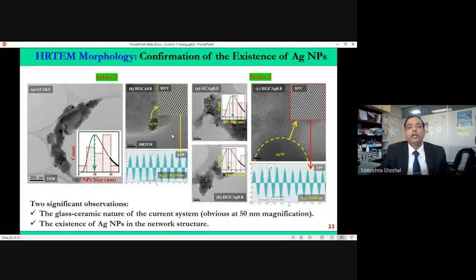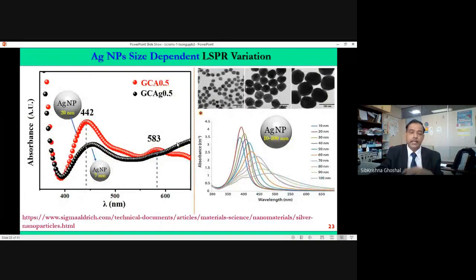Well, how do we know nanoparticles are formed? Then we take every glass ceramic from this, then we do TEM and also HRTEM, again measure the SAED, fast Fourier transform, then we see again very nice lattice fringes are formed, and that's how we are getting the nanoparticle. So it is ensured that the nanoparticles and crystallites are there.